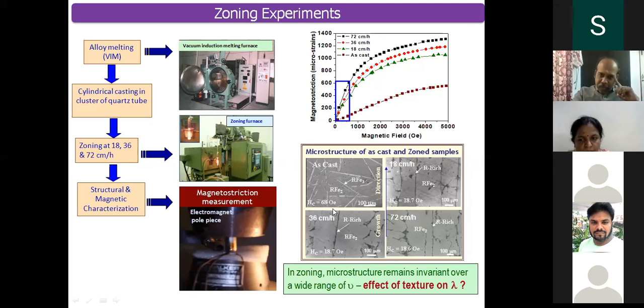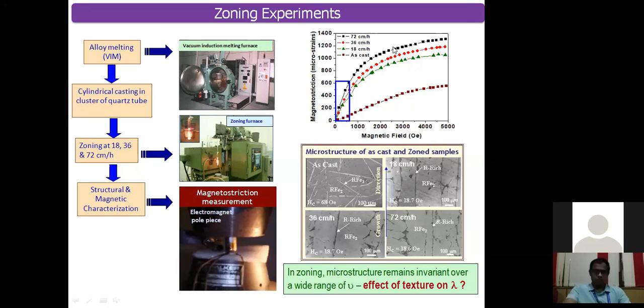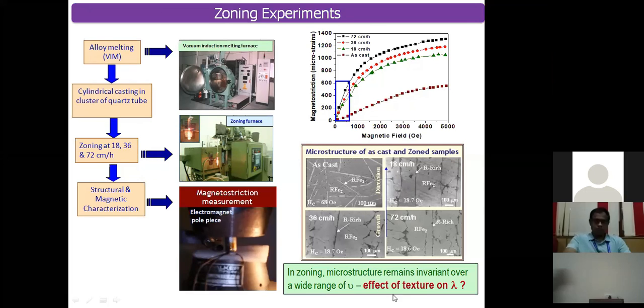But when we tried to measure the magnetostriction, to our surprise, the as-cast alloy did not show much magnetostriction. This basically happens because you have an RFe3 phase which is magnetic, and it is also compensating the magnetostriction from the RFe2 phase. But now I don't have an RFe3 phase, and still the magnetostriction values are found to be different. The microstructure is not showing much. So we wanted to see, is there any effect of texture playing a role in this?